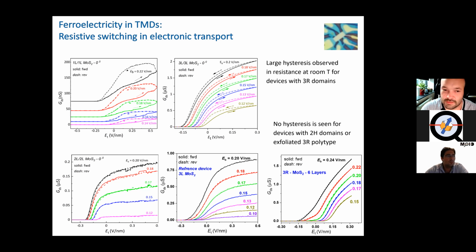So the second reason is, of course, the domain walls, and we don't really know what kind of scattering processes happen at the domain walls. Now, by rearranging the domains inside a sample, we may create more domain walls on the path of the electron from source to drain. And if they scatter, which they actually should, that may significantly influence the conductivity. But at the moment, we haven't actually measured an isolated domain wall. That would be the next step in this saga.